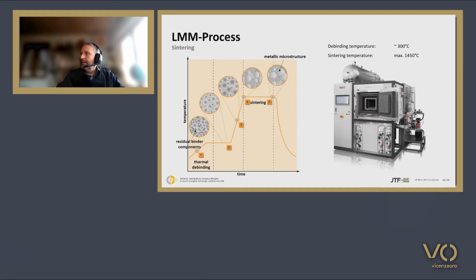We sinter in a retort furnace. As said, the debinding and the sintering is a combined procedure, so the parts are not removed in between. We can go up to 1450 degrees here, which means that most materials could be sintered that way, and the sintering temperature is about 80% of the melt temperature. But that's just a rough rule of thumb. Of course, this has to be optimized to the process and the parts.